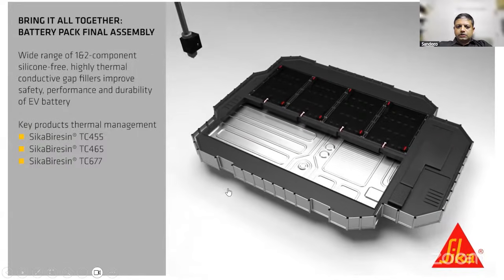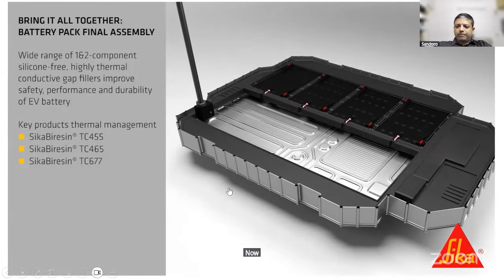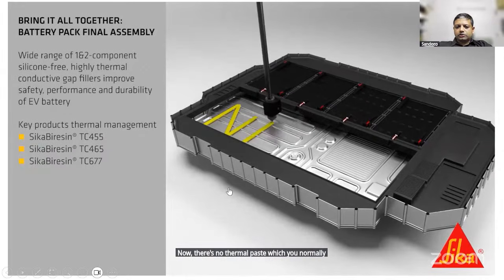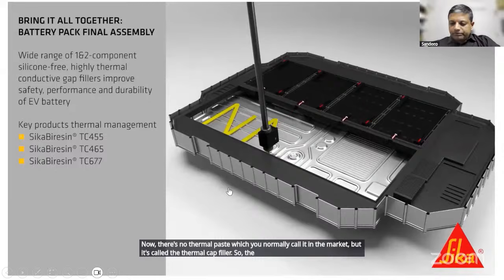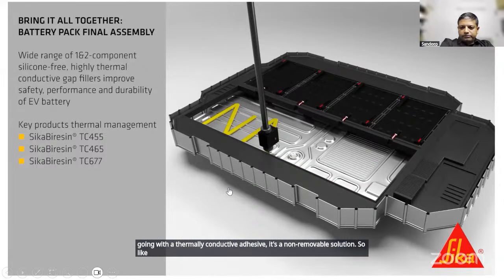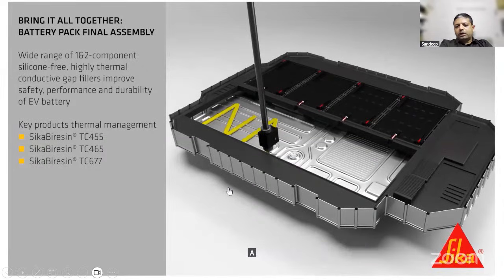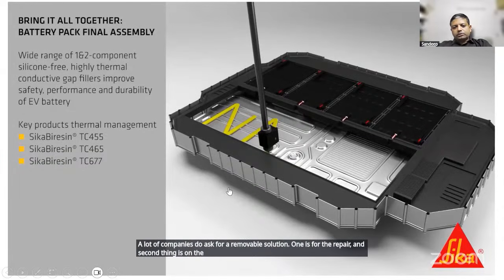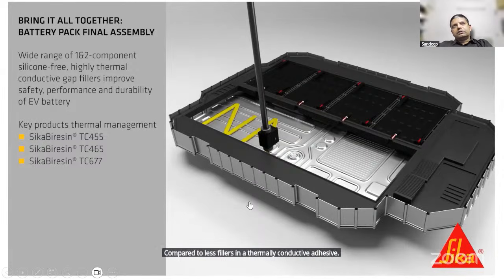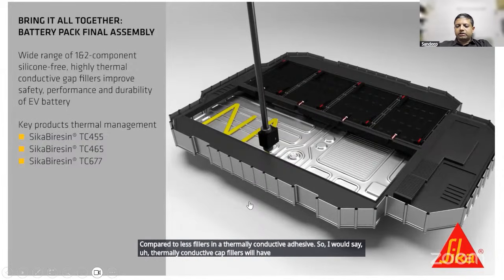Now, this is a thermal paste solution. The main difference is that if you are going with a thermally conductive adhesive, it's a non-removable solution. Like I mentioned in the beginning of this session, a lot of companies do ask for a removable solution. One is for the repair, and the second is for recyclability. Thermal gap fillers are different from thermally conductive adhesive because thermal gap fillers have more thermally conductive fillers compared to less fillers in a thermally conductive adhesive. I would say thermally conductive gap fillers will have 80% conductive fillers and 20% adhesive, and vice versa in the case of a thermally conductive adhesive.